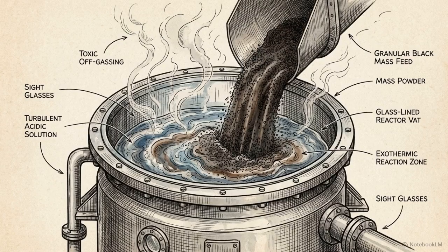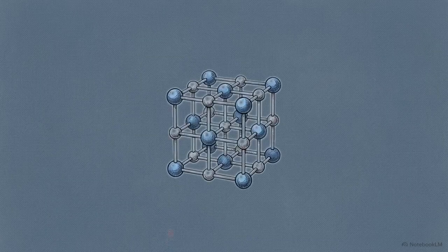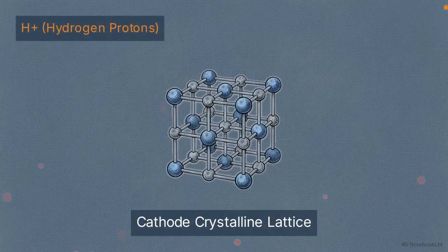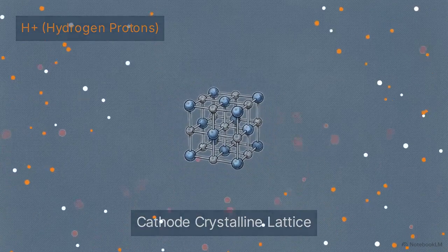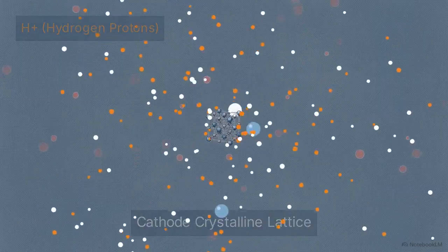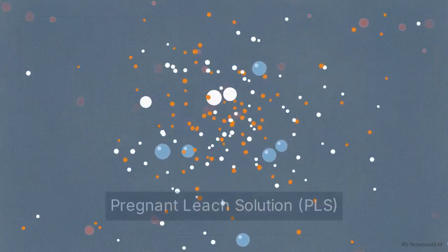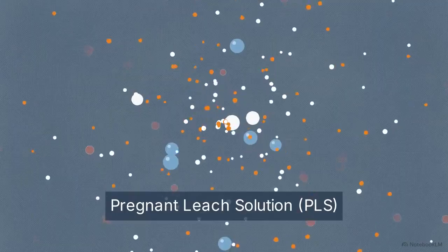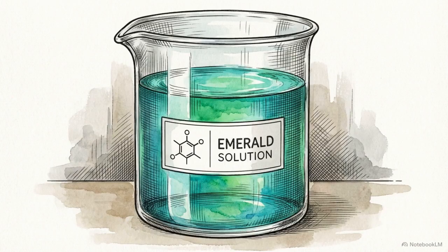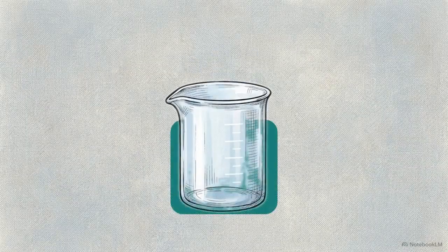Recyclers submerge the black mass in highly concentrated inorganic acids, primarily sulfuric acid, combined with hydrogen peroxide. At the molecular level, high concentrations of hydrogen protons from the acid aggressively bombard the crystalline lattice of the solid cathode material. This forces the metal atoms to detach from their physical bonds and dissolve into the fluid. This creates the pregnant leach solution, or PLS. The PLS is a highly acidic, aqueous liquid saturated with dissolved lithium, nickel, cobalt, and manganese.